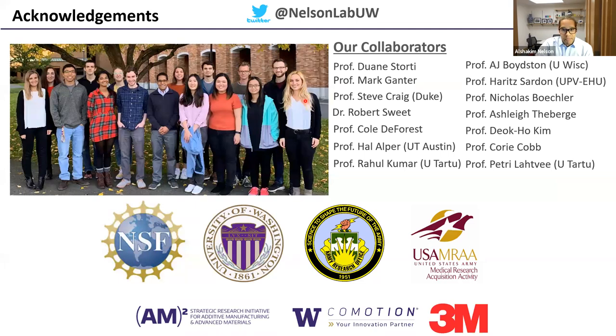If I don't answer your question sufficiently, please feel free to unmute yourself or to add additional questions in the chat. So, pore sizes of these hydrogels, that's a really good question. First I will say that the hydrogels for the F127 BUM are 30% by weight polymer, 70% water, so they are mostly water. When we look at these hydrogels after lyophilizing them, by SEM, we see pore structures on the order of 5 to 10 microns. It's always hard to tell how representative those structures are after you lyophilize them, but maybe that gives some indication of how large those pores can be.